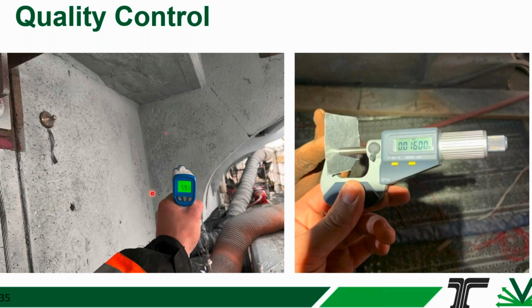the bond. On the right, one of the other things that will be specified is to measure the thickness of the zinc, and that will include removing some sections and physically measuring the zinc and then touching up those areas. And probably the most important quality control thing that is going to be specified is to measure the bond of the zinc to the concrete surface.